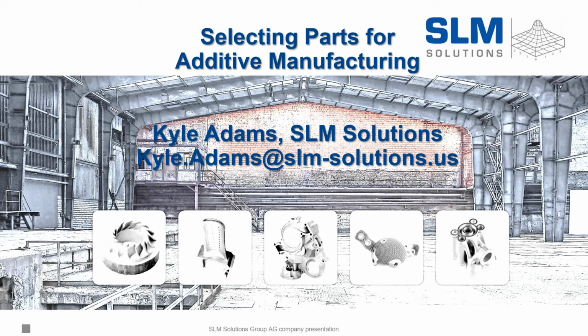Good, thank you. Is that hipping process done to increase density, which I think it is, right? So what are the typical densities in aluminum before and after the hipping process? Typical densities are always 99.8 and higher. We like to say if you see even 99%, that we have a problem and we'll go looking for a solution. That being said, with the hipping process, there are certain applications and development work right now in titanium where